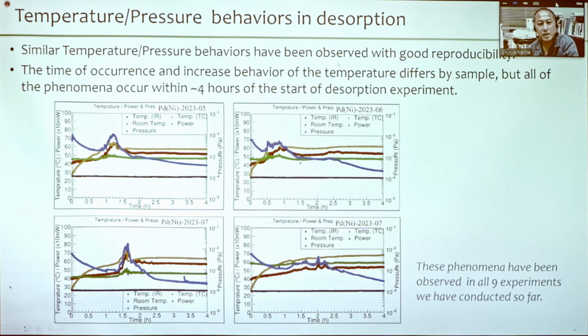Similar temperature and pressure behaviors have been observed with good reproducibility. The time of occurrence and the increase behavior of the temperature differ by sample, but all of the phenomena occurred within the 4 hours of the start of the desorption experiment. Yeah, I put the result of the 4 experiments, 4 runs. So for each case, you can see the temperature increase with the pressure increase here and here and here. And these phenomena have been observed in all 9 experiments we have conducted so far. So with good reproducibility, we have seen that.